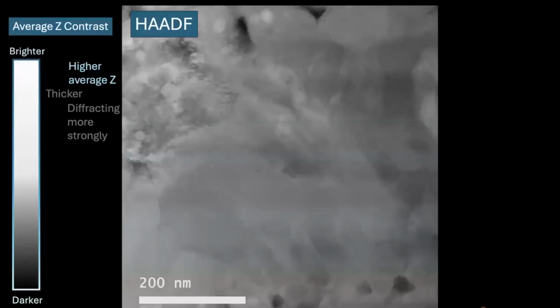So now I'm going to talk about the inclusion poor region. I have a bunch of HAADF images. I can't confirm that some of this stuff right here is Reidite. That's a work in progress, but it's brighter than zircon in HAADF imaging, so it has a higher average atomic number. I did EDX chemical mapping. It shows up as a zirconium silicate, just like zircon, with no chemical differences. And it has the habit of microstructural Reidite lamellae. So it's likely Reidite, but I can't 100% confirm. That's something I'm working on right now.